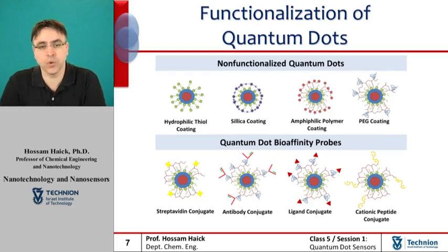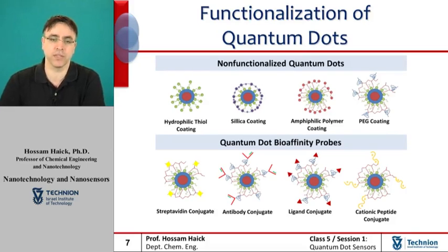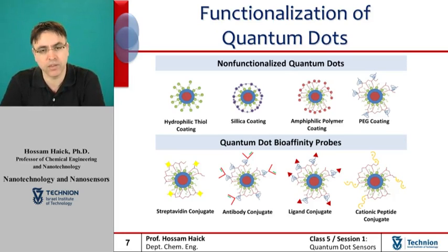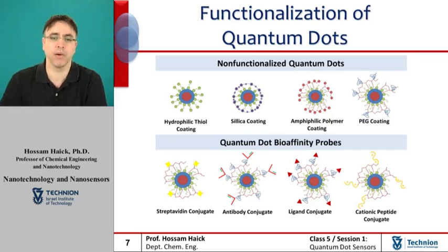Further examples include quantum dots that are encapsulated with or in amphiphilic polymer, which form highly stable micelle-like structures. In this case, any of these quantum dots may be modified to contain polyethylene glycol, or PEG, to decrease surface charge and increase colloidal stability. Water-soluble quantum dots may be covalently or electrostatically bound to a wide range of biologically active molecules to render specificity to the biological target.